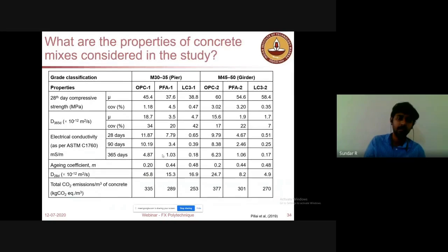So we did a study where we made 6 concretes with ordinary Portland cement, Portland Pozzolana cement, that is PFA, and LC3, which is a ternary blend of limestone and calcined clay. We made 2 different concrete grades, and we took durability data from the concrete, like the diffusion coefficient, and calculated the aging coefficient, which gives us the pore structure evolution over a period of time.